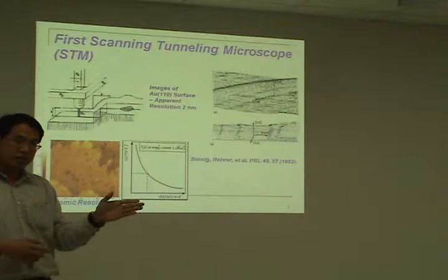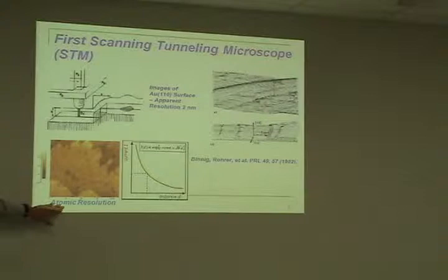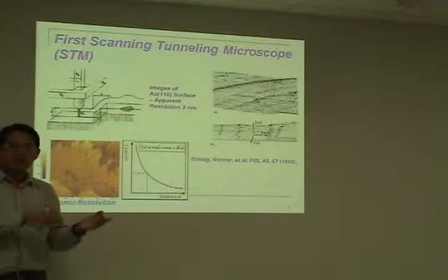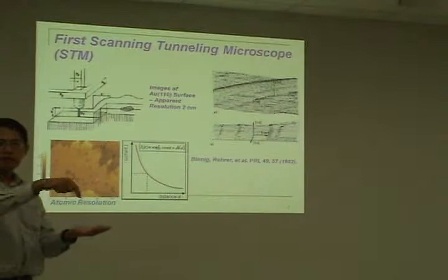The first work was a tip scanning on a gold (110) surface, and later work shows atomic resolution — you can see the steps, individual atoms, and individual vacancies. The tunneling current is extremely sensitive to the distance between the tip and the sample; it decays exponentially with distance. That is why STM has very high lateral resolution and also high Z resolution.